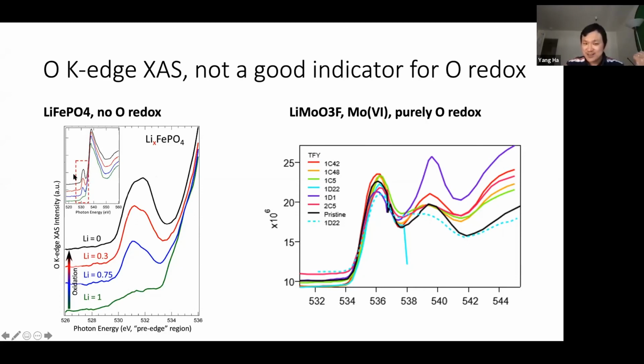of the oxygen redox, which suggests the oxygen pre-edge only correlates with iron redox, not the oxygen redox. In this example, it is a lithium molybdenum oxide fluoride case. This is a material designed by our collaborators. It starts from molybdenum 6+, so it really has no place to further oxidize. So the whole cycle of this material is purely on oxygen redox.